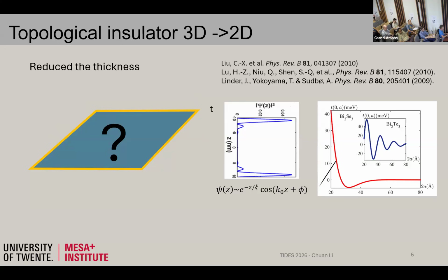So when this happens, we are basically facing again a topological to non-topological transition within this 2D surface state. That means once you have the gap in the surface and you are in this topological regime, you form 1D edges. So that's why we go for this ultra thin system, to see what's going to happen.